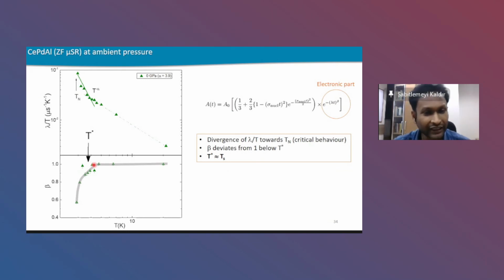The involvement of beta was there just above the ordering temperature. There is a characteristic temperature denoted by T star, below which we have seen that the beta values deviate from 1. And interestingly, we have seen that T star, this characteristic temperature, is more or less exactly at the same point, within the error bar, as the temperature scale of the hump in the susceptibility.